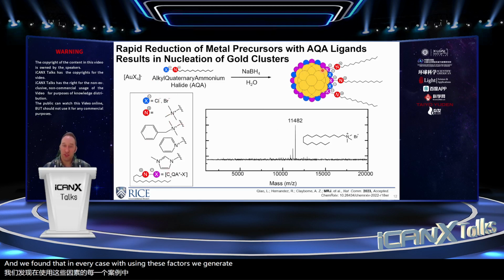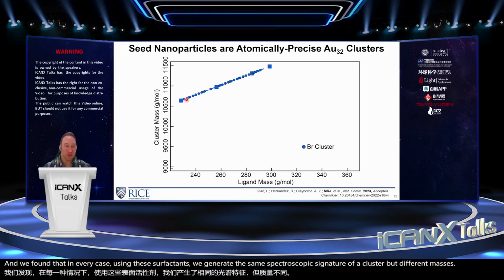We bought every kind of alkyl quaternary ammonium surfactant we could find. Some of them we had to synthesize ourselves. And we found that in every case, using these surfactants, we generate the same spectroscopic signature of a cluster, but different masses. So this is a summary of those data.